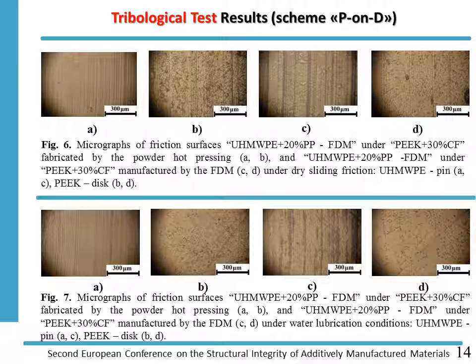The next slide illustrates the micrographs of wear track surface topographies, also for various conditions of testing. What is of particular interest is that for the condition of water lubrication, with absence of wear, we register just an absence of any traces on the sliding surface. But in the case of dry sliding, you see that the temperature is increased, and it gave rise to some melting and plastic flow of the surface layer, and traces of such plastic deformation are observed on the surface. But anyway, the result is positive. Such materials might be employed for manufacturing of friction pads.